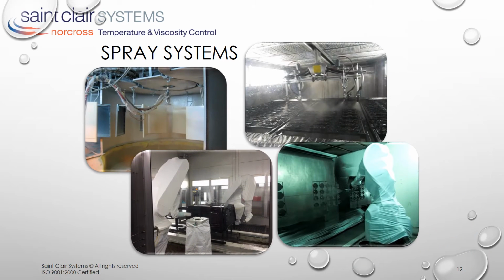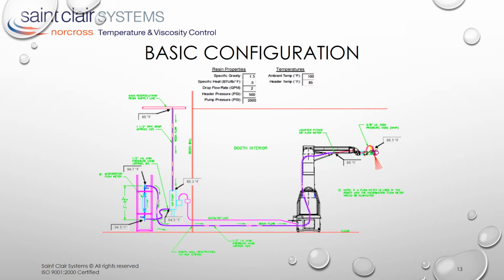There are as many different spray systems as there are engineers to design them, but they all boil down to the same basic configuration. In addition to the basic system layout, this thermal model shows calculated temperatures at various points throughout the system. Though the temperature may be important at various points throughout the fluid delivery path, to maintain a consistent viscosity and to control pressure drop, there is only one temperature that determines the quality of the finish, and that's the temperature of the paint leaving the nozzle. This is commonly referred to interchangeably as the point of application, point of dispense, or point of use.